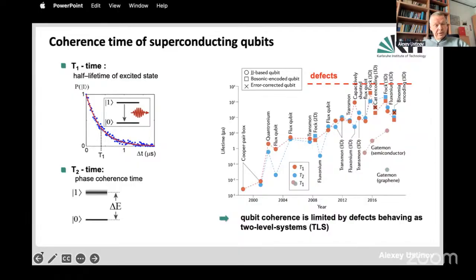So we are talking about the coherence, which actually is limited by, generally speaking, two major processes characterized by times T1 and T2. So the characteristic time of T1 is basically the relaxation due to the interaction with the environment. So if you excite the system from ground state to excited state, then it relaxes by emitting a photon to the environment. This photon for superconducting qubits is in the microelectron volt energy range, which corresponds to a frequency of few gigahertz.